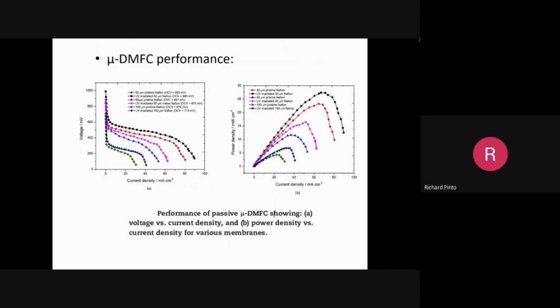Now, what is the effect finally? Which is seen in the power output. As you see the polarization plots again here, voltage versus current density, milliamps per square centimeter. The power density versus current density, milliamps per square centimeter. Here is the milliwatts per centimeter square. See, here you see the optimum exposed membrane. So this is the highest one, 50 micron, UV exposed.